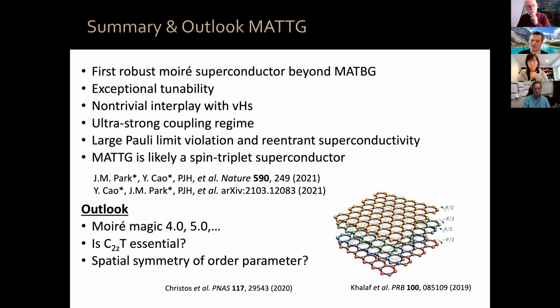So it is not entirely understood, but what our experiments in the trilayer graphene case have shown us is something very interesting, which is superconductivity emerges from the state of your system where you're occupying two flavor-polarized states. In other words, you have two Fermi surfaces in your system, as opposed to 4, 3, or 1, okay?